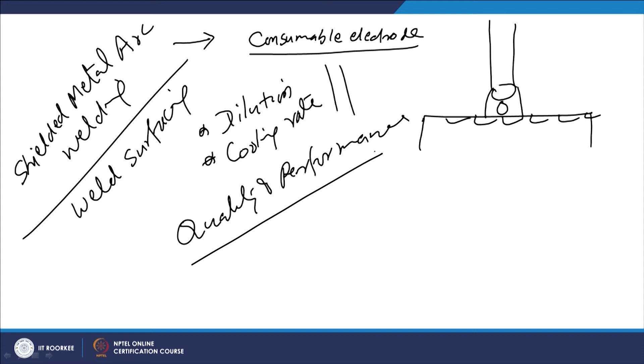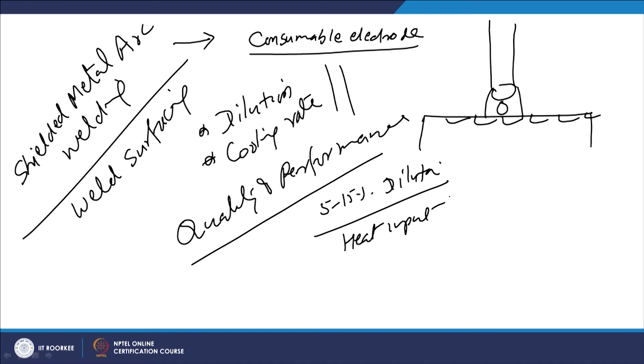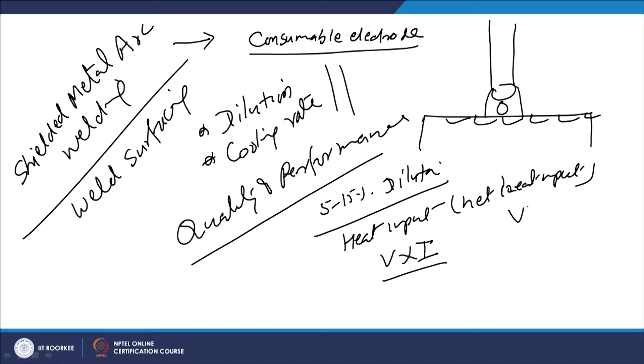As far as the shielded metal arc welding process is concerned, normally 5 to 15% dilution is observed, but dilution is also affected by the kind of heat input given — specifically the net heat input. Heat input during arc welding is obtained from the product of arc voltage and current (V×I). The net heat input is obtained by dividing V×I by the welding speed s, because the arc travels continuously during deposition. So V×I/s gives us the net heat input, also expressed as H_net.